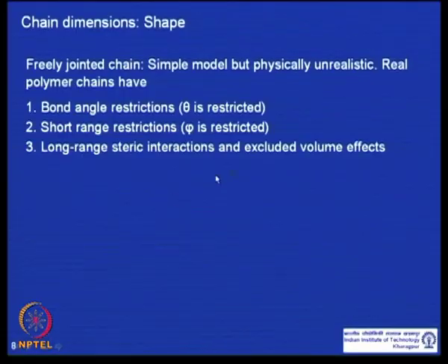So there are actually three interactions: bond angle restriction, short range restrictions coming from the single bond rotational restriction, and long range steric interaction and excluded volume effect, which we will encounter one by one and see how the dimension or the size of the polymer changes.